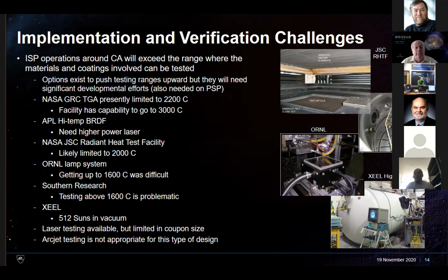We have a vacuum furnace at our place. They had a vacuum furnace up at Hopkins that had different vacuum systems on it. So we're talking about between 10 to the minus 3 and 10 to the minus 5 torr. We were getting different results just based on the vacuum pressure we would see in the system. Again, there are materials in there, and if there's some oxygen in there, the oxygen is doing things. So you have to set up this system and run with it so you know what it can do. We did a good amount of testing down at XEEL, which kind of broke away from Auburn.